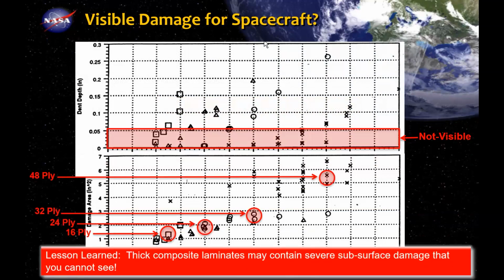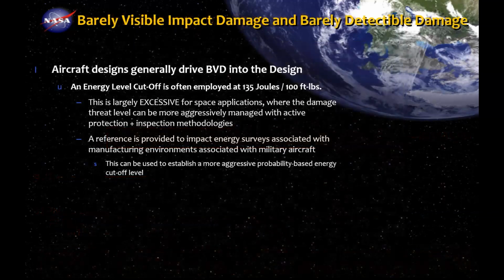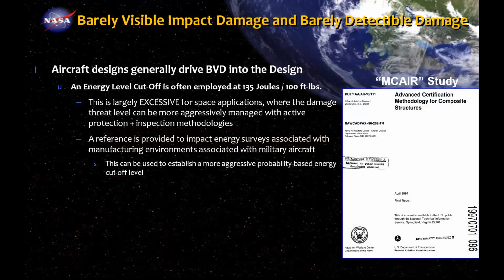This is data on dent depth versus visible inspection. The takeaway is that for thicker laminates, you can have almost no dent depth, which is the plot on the top. Look at the X's, and you'll see at very high energy levels, maybe 100 foot-pounds or so, I've got dent depths of 50 thousandths. But yet if I look at the subsurface damage area at that 48 ply data point, I got 5 square inches of delamination. So the point is visible damage isn't very reliable for us in these structures. Okay, next slide.